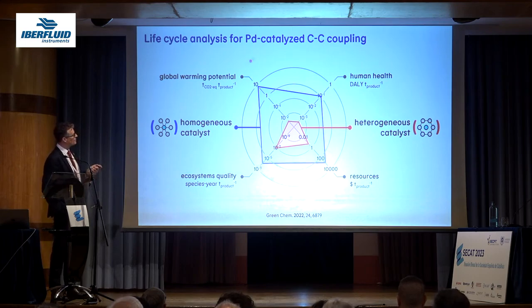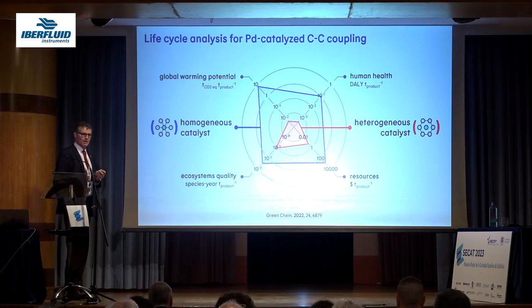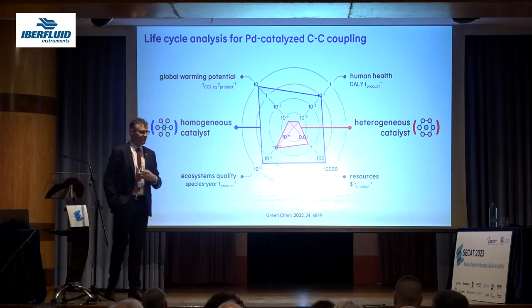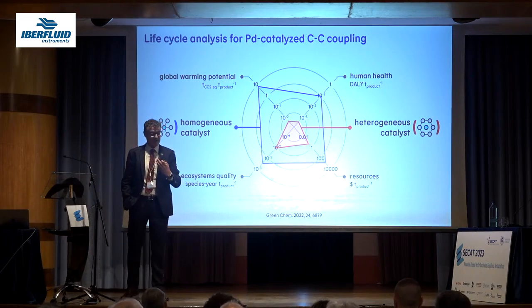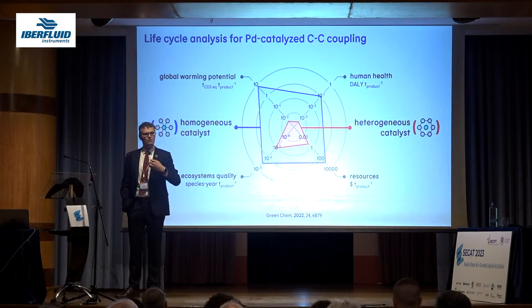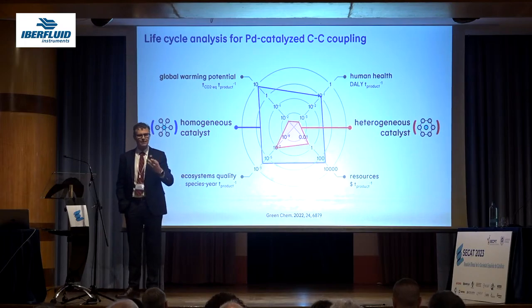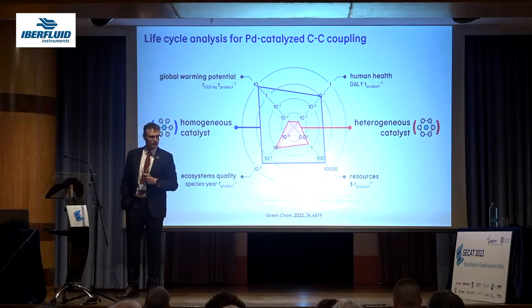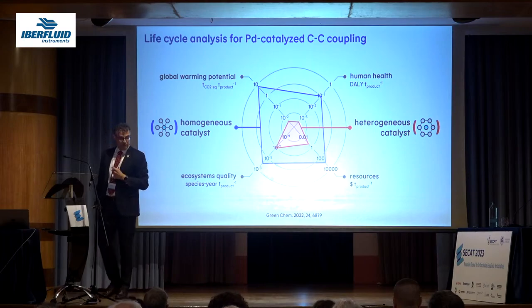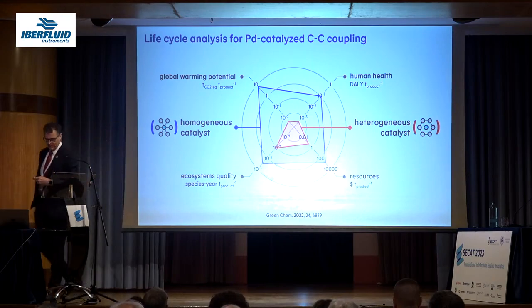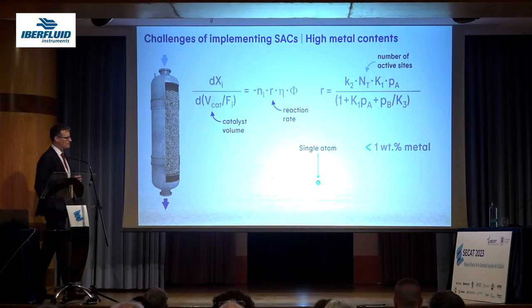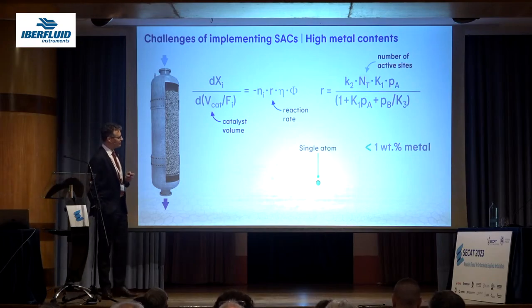If you move for a palladium catalyzed carbon-carbon coupling from a standard homogeneous catalyst to heterogeneous catalyst, some of these LCA indicators are improved by not 10 times, but sometimes 100 times, and 1,000 times, orders of magnitude. And that is because of the much better recyclability and reusability of a metal in a solid form compared to a soluble organometallic complex.